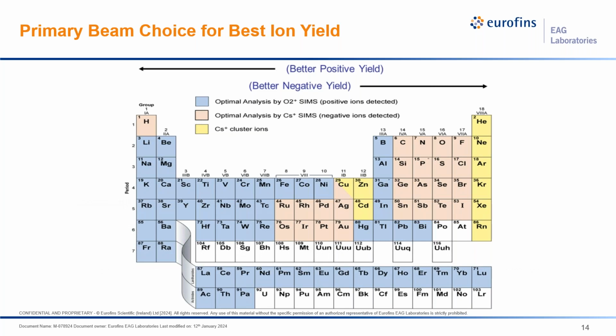The periodic table is shown here, and the choice of primary ion, or at least detection mode, is color-coded. As expected, many of the metals on the left side are optimally measured with oxygen bombardment as positive ions. The non-metals on the right side are conversely detected as negative ions. And then there are a few, as I just mentioned, some of the metals that are best measured as clusters, and all the noble gases are also better detected as cluster ions.